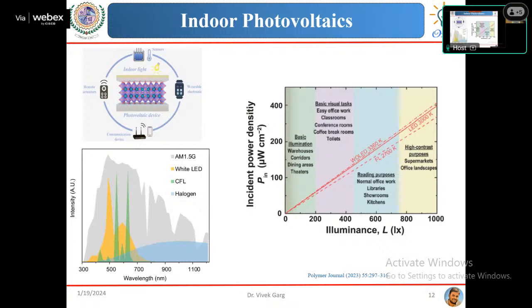In a traditional solar cell, the peak is around 500 nanometers, so the band gap requirement for outdoor energy harvesting should be around 1.3 electron volts. There is a very big change in terms of the material itself. So you cannot utilize traditional outdoor solar cells, or the materials used to harvest outdoor light. You need a specific material where the band gap requirement is totally different, right? In indoor cases, the band gap requirement is around 1.9. In outdoor cases, it is 1.3. So based on this, we have assessed the band gap requirement for a material in indoor conditions, right?